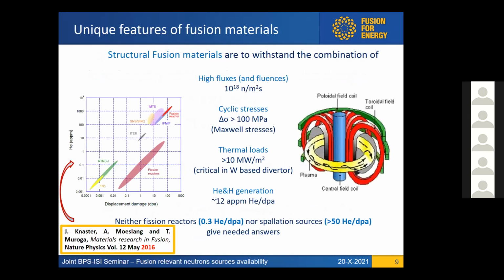In fact, if one compares the fusion materials with fission materials, all the difficulties that the fusion materials are going to undergo in a nuclear reactor, we can see that the solicitations are substantially stronger. We have to deal with very high fluxes. Okay, materials in fission reactors also do. But we'll have to face cyclic stresses, which in fission reactors we don't have. And in particular, due to Lorentz forces, they can be above 100 megapascal. Thermal loads in the divertor above 10 megawatts per square meter, which can even reach 20. And helium and hydrogen generation at 14 MeV of about 12 atoms per million of helium per dPa, which is enormous.